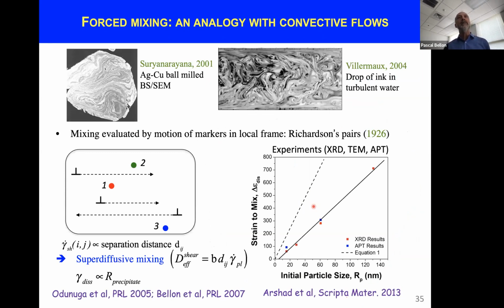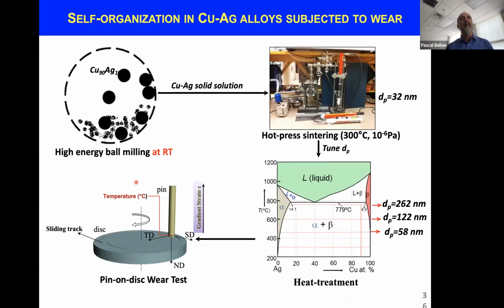That is a concept that was introduced about 100 years ago by a British scientist, Richardson, realizing that when you have markers in the microstructure, and if you imagine dislocations or flows shearing these markers, the larger the separation distance, the more likely it is that the pair will be sheared and the more effective the mixing is. And this is the key reason for this self-organization. And we tested that super diffusive mixing is indeed taking place in ball milling.